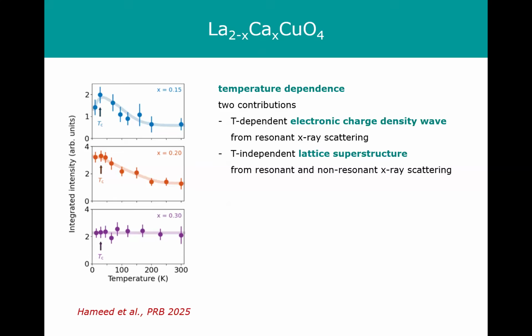And there's quite a distinct doping evolution here. So at low doping, let's say on the upper panel here, 15%, you see a clear temperature dependence, consistent with what has been seen in prior work. You can even see, although it's not so pronounced here, evidence of competition between charge order and superconductivity, meaning that the charge order peak decreases in amplitude when you cross TC.